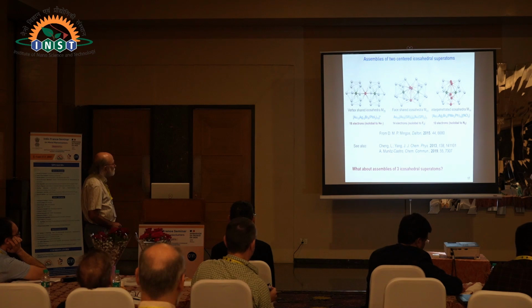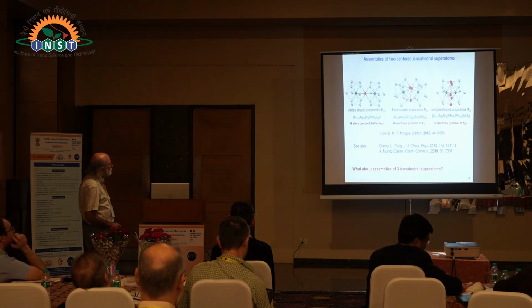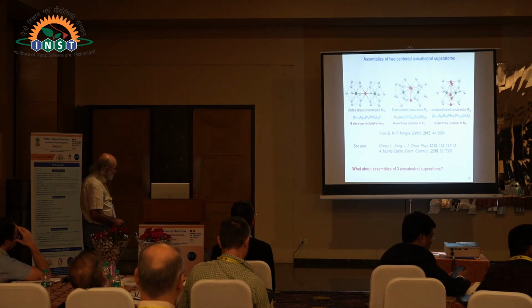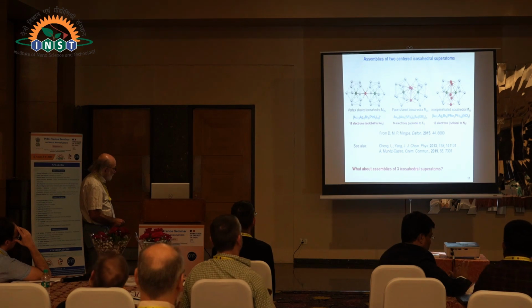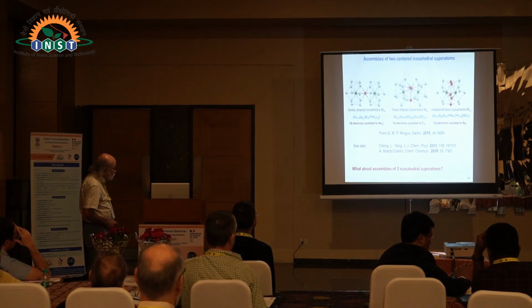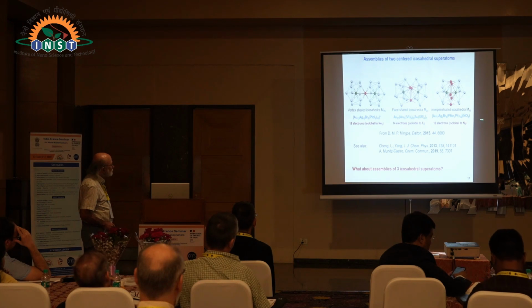It's equivalent to the van der Waals molecule, Ne2, no bond, no significant interaction between the 2 icosahedra. When you increase the compacity, face sharing now, you can have 14 electrons, this system, equivalent to F2. And when they are interpenetrating, meaning that the 2 icosahedra are sharing the red atoms and the green atoms, then you can have 10 electrons, compacity increased.